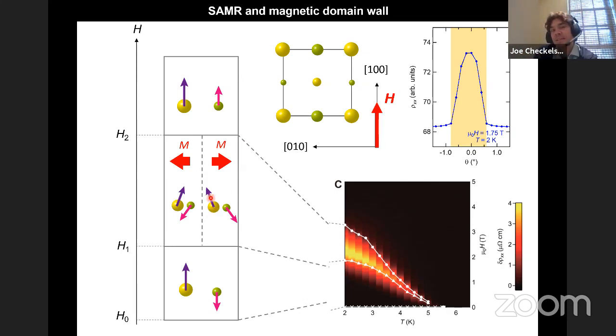And the interesting thing in this system is that because the spins are imbalanced because of this ferrimagnetic ordering, you have a little bit of transverse magnetization associated with these two types of magnetic orders. And so in the case where you have the field aligned exactly along 100, and you turn it up and go through this transition, the energy of these two magnetic states is the same. And so in the context of magnetism, you would then immediately understand that I will get domains of those two magnetic orders.